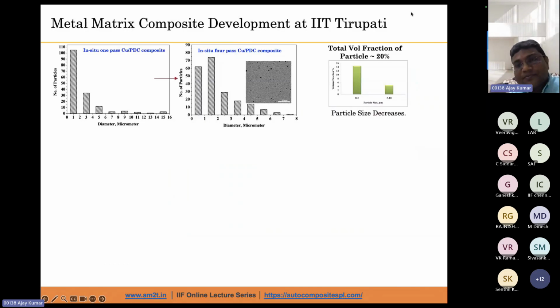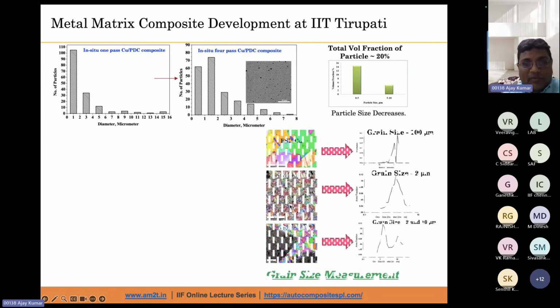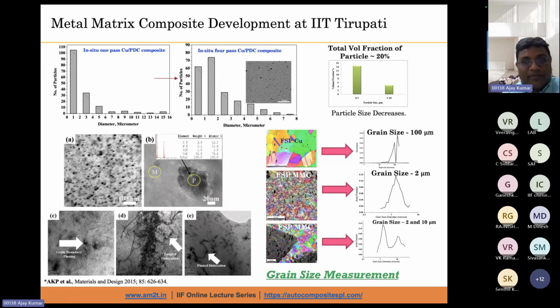So now I will discuss the work which we are doing at IIT Tirupati and some of the work we have reported. As I mentioned, when we make composite materials using the casting process, casting is the most versatile process, and it is acceptable to most of the industries. We can make large-scale components, but a couple of fundamental challenges we face in cast MMC are low toughness and uniform dispersion of the second phase particles. So here we have used solid state processing. We have combined the liquid state route as well as the solid state process route, so that we can get better properties and address the challenges we face in cast MMCs.